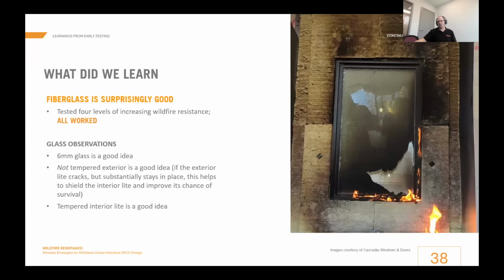First one cracked. When tempered glass breaks, it shatters violently. And often a chunk falls out, as you can see in the bottom right corner of this window. Do you think if we repeated this test with this glass 10 times, that all 10 times that piece or smaller would fall out only? Or do you think that there's some instance in that period of 10 times where most of the glass happens to fall out? Because it's a very random break pattern. So we think that if a larger piece of this outer pane of glass happened to fall out, then it would more fully expose the inner pane of glass to the fire that was continuing on, and it would increase the risk of failure to the inside of the glass.